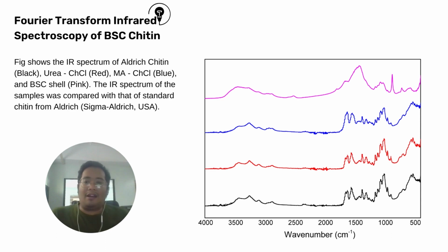Next, the FTIR also showed promising results, as it shows the chitin extracted was an alpha chitin. Also, compared to the blue swimming crab shell, which is the pink spectra, it showed that the protein and the calcium carbonate peaks were removed after the DES extraction.